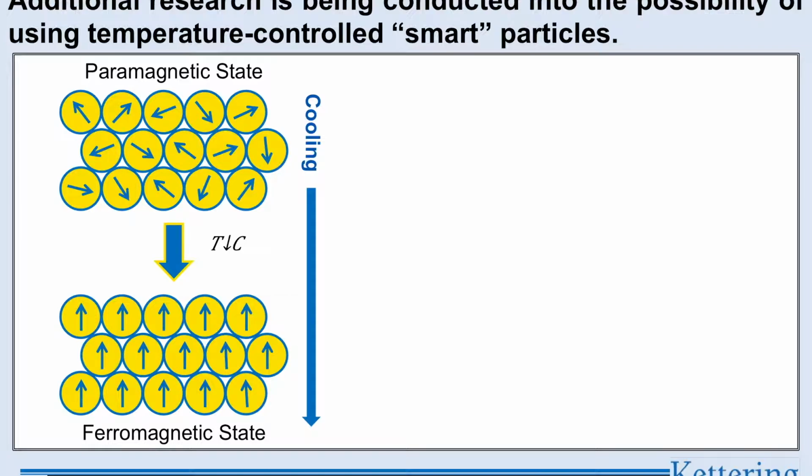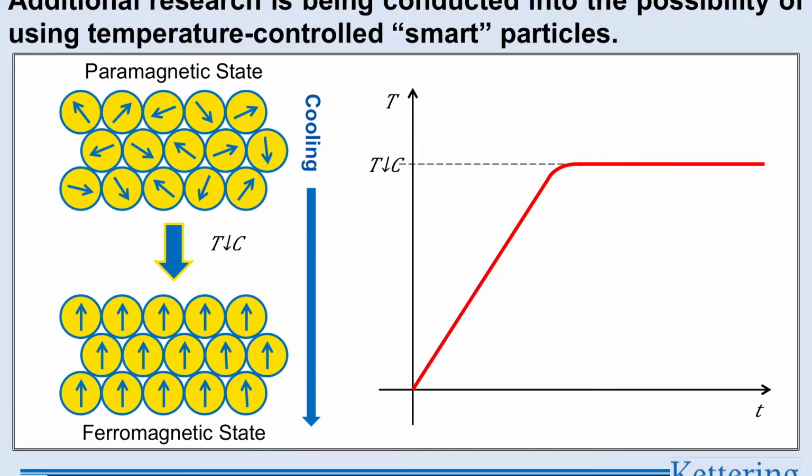So we're calling these smart particles that have what we call a Curie temperature right at that magic range. What we could do is drive the magnetic field as hard as we want, and these will heat up to that temperature and then just hover around it. As they go above it, the magnetism essentially shuts off and they cool down a little bit. When they come below it, it turns back on and they heat up. It's like 45 degrees is what you're thinking. Well, somewhere around there.